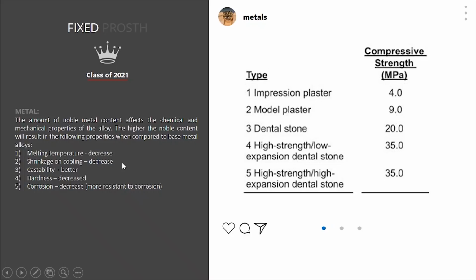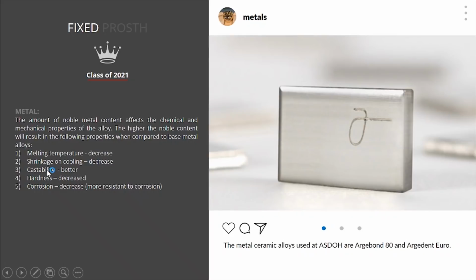So if you think about the difference in shrinkage, what's a good way to compensate for that? Well, you can compensate by using a different type of stone when we use a base metal which shrinks more. Oftentimes what you're going to find is labs that use base metals for their crowns will use a high strength, high expansion stone to compensate for the fact that the base metal shrinks more. If you have a stone that expands more, it'll compensate for the metal that shrinks more to get that net zero effect.